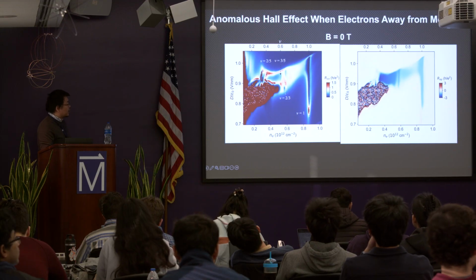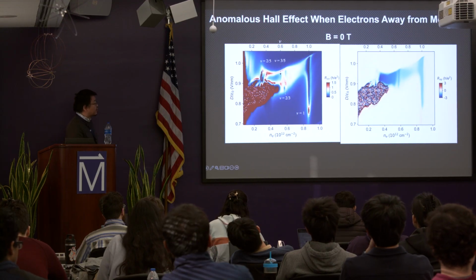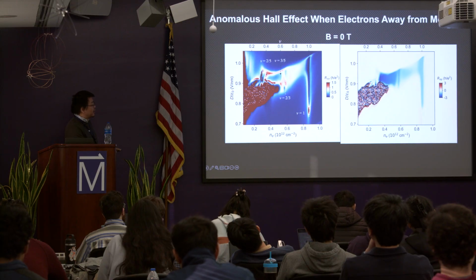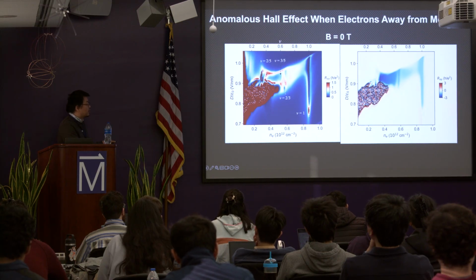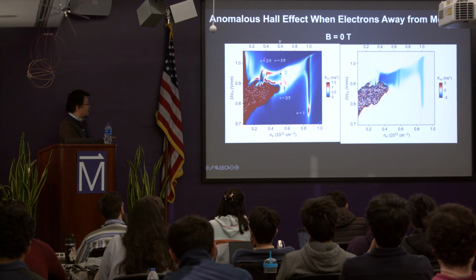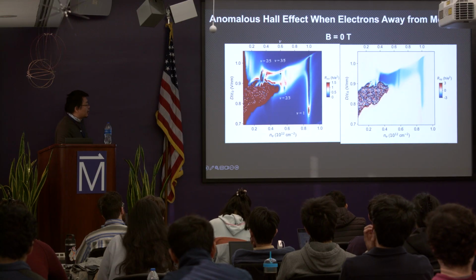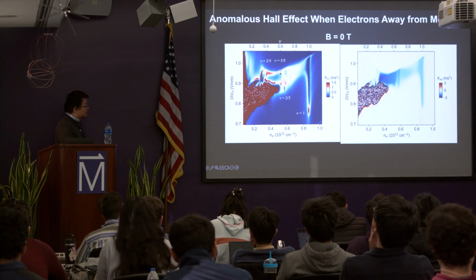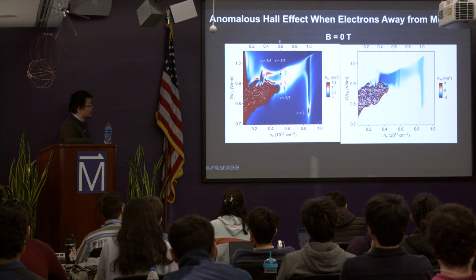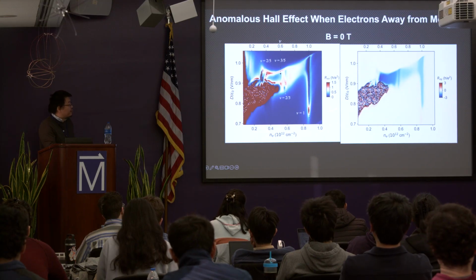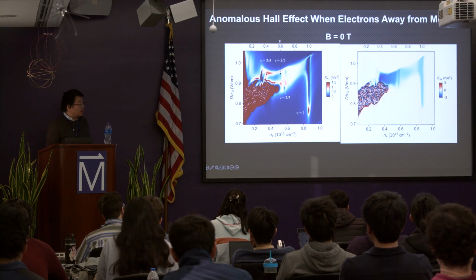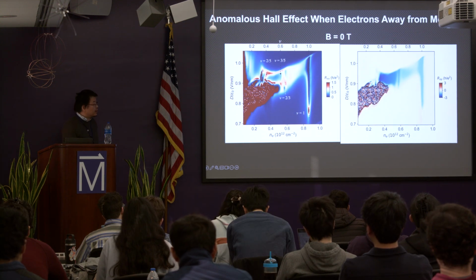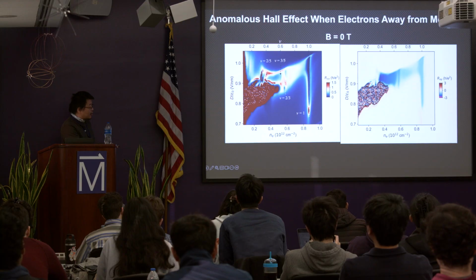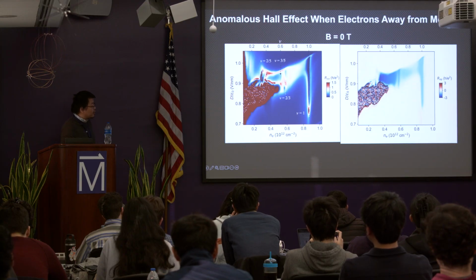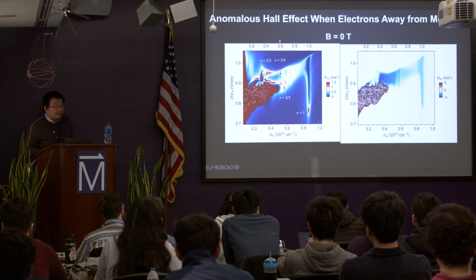From the longitudinal resistance map, we can see a very clear dip that is aligning with filling factor equals 1, and there are some features that may be aligning with certain fractional fillings. Around this region, there's actually a lot of anomalous Hall signal. Both maps are taken at zero magnetic field. This blue color means a non-zero signal, and you can see the blue already gives you around h/e² level of anomalous Hall signal.